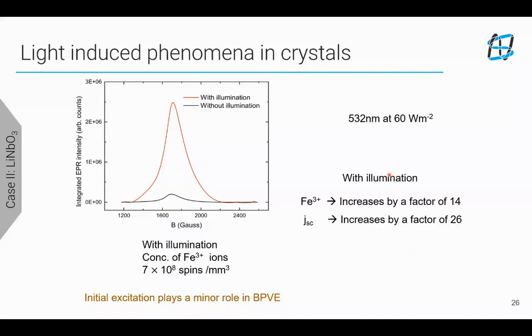So what we saw was, with illumination, from the EPR, the Fe3+ ions increased by a factor of 14. But from the electrical measurements, the photovoltaic measurements that we've seen, the short circuit current increases by a factor of 26. That's already two times higher. So there's something else which has happened.